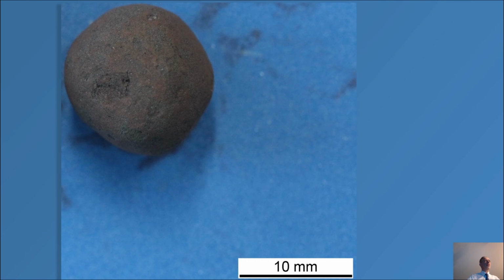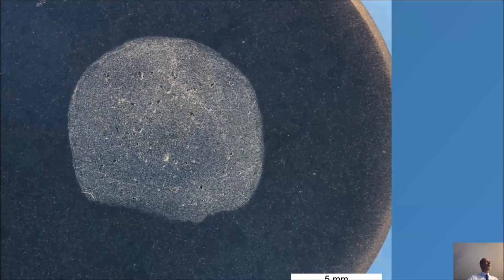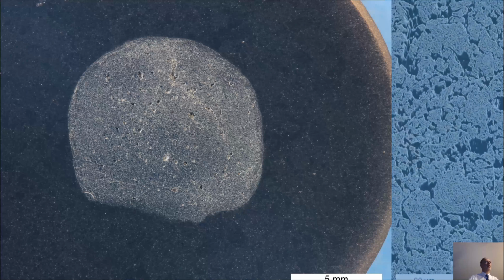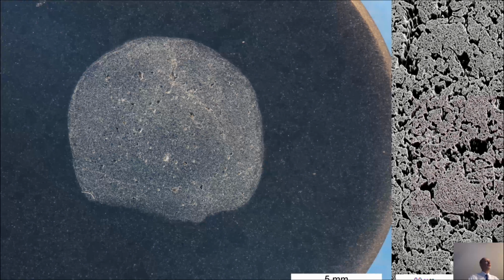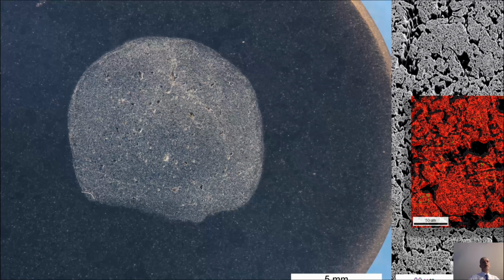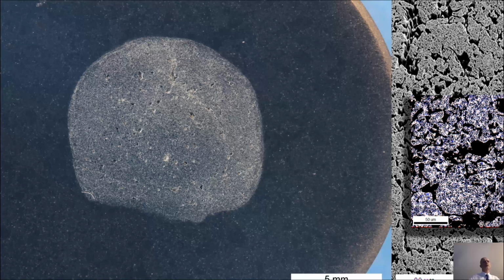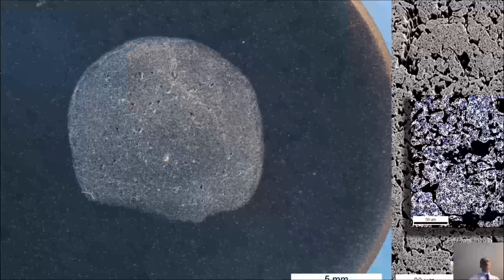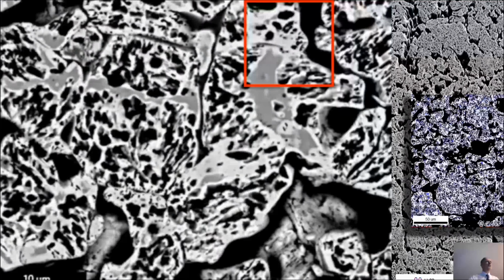Let us have a little fly through the wüstite pellet, to the hematite pellet. Originally the pellet is hematite. So we cut it through and you see a modest porosity which is inherited from the processing step. That was originally designed for classical direct reduction processes, because this is a so-called direct reduction pellet. And you see that this material has a very complex microstructure consisting not only of multiple pores but also of multiple interfaces, grain boundary, and internal free surfaces.